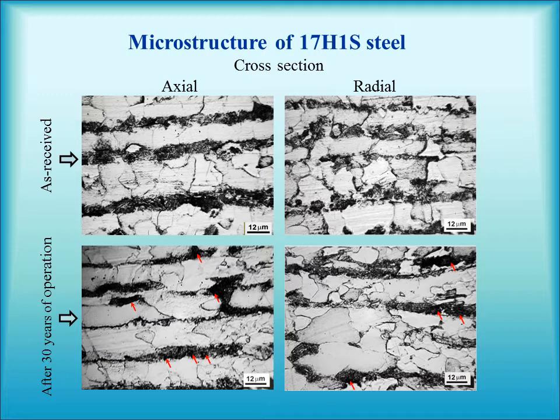Let's consider the microstructure of the steel 17H1S in more detail. The texture is clearly revealed in both axial and radial cross-sections. Perlite interlayers in the steel in the as-received state, in axial directions, are almost continuous and considerably longer than that in the radial directions. Here perlite strips are often interrupted by some separate grains of ferrite.